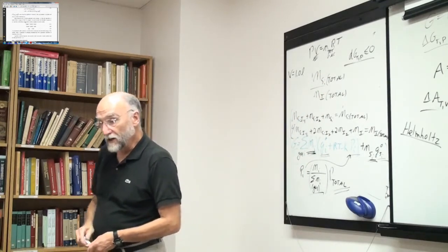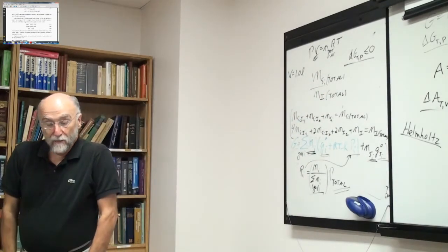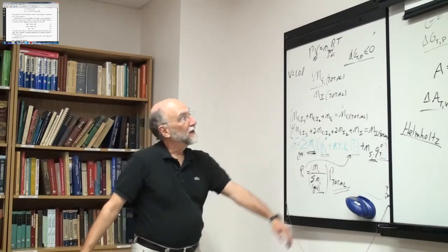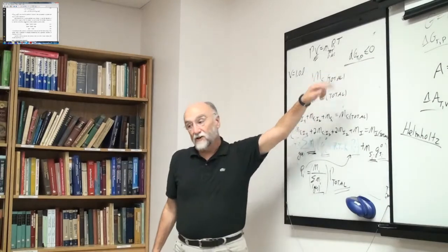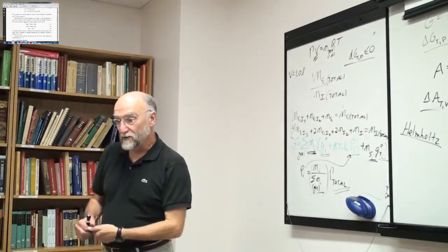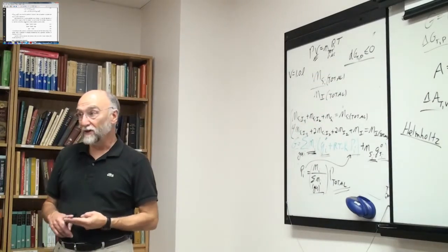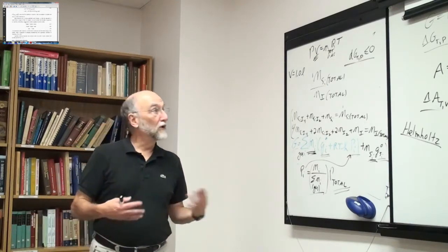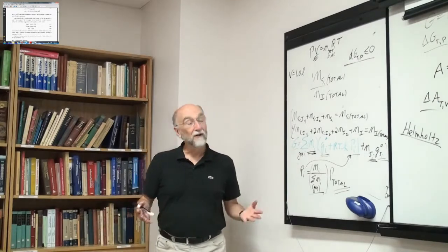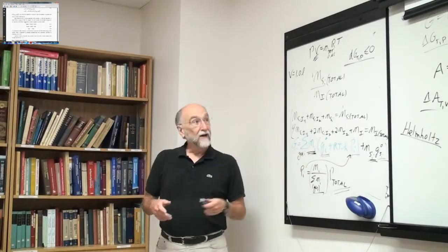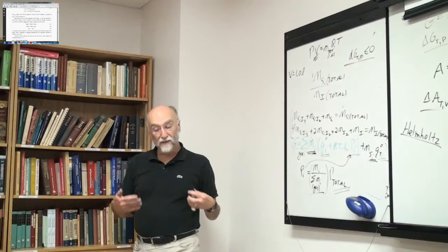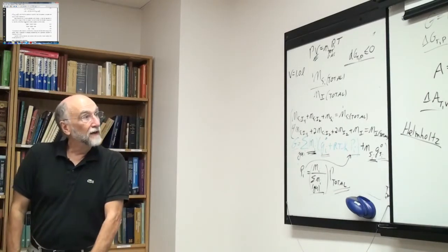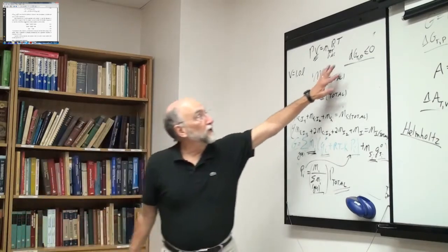way of expressing the second law in terms of writing computer programs to minimize Gibbs energy, to find equilibrium, because generally it's easier to express thermodynamic properties of materials and solutions in terms of temperature, pressure, and composition than in terms of other variables. But even if it weren't easier, we like to do it just one way, not several different things. So everything is written in terms of Gibbs energies, thermodynamic properties, and the tables are all expressed in terms of T, P and composition, and so we can use that.